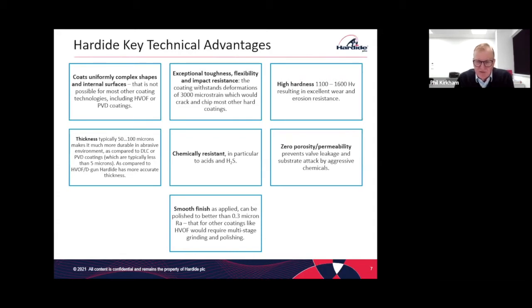And that was developed particularly for the oil and gas industry, used on downhole tooling, which is very aggressive chemicals and also very high wear rates with particles of sand and rock impacting the component. And that's our most common coating. It's probably 90% of what we do is in that range.